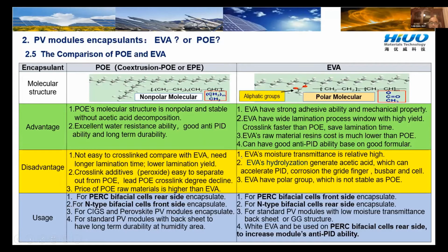So let's look at the disadvantages. EVA's moisture transmittance is relatively high. EVA hydrolysis generates acetic acid, which can accelerate PID and corrode the grid fingers, busbar, and cell. So EVA has a polar group, which is not as stable as POE. So that is the disadvantage of EVA.